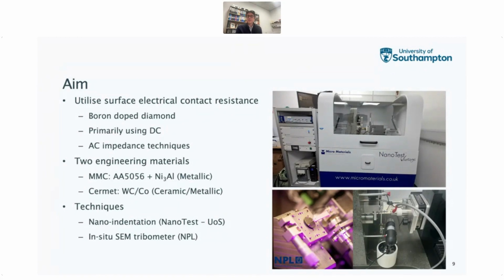So the reason we chose those two materials, I mentioned at the beginning, was the metal matrix composite. It's normally a metallic type of material. It's a metallic matrix with an intermetallic, a distinct intermetallic phase in there. So we hoped we could get some distinct correlation between that. But we also wanted to try it on something that was quite distinctive in terms of its conductivity. So the Cermet offers this possibility as being a ceramic within a metallic binder matrix. So that was the choice of the two engineering materials.